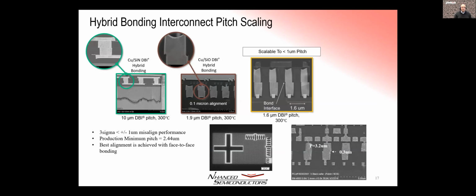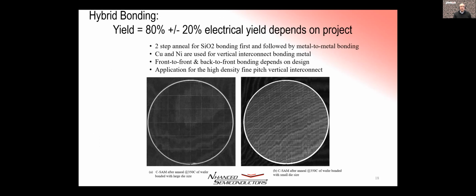Here's some pictures of interconnect that we've done. Most of what we do is 3 to 5 micron pitch. And as I mentioned earlier, the smallest pitch we've done to date is 0.8 micron. Here are some CSAMs, which are scanning acoustic microscopes of what the bond interface looks like. The lines in X and Y that you see are actually the edges, the boundaries of the chip. You're seeing the scribe lane areas, which reflect the acoustic energy a little differently.